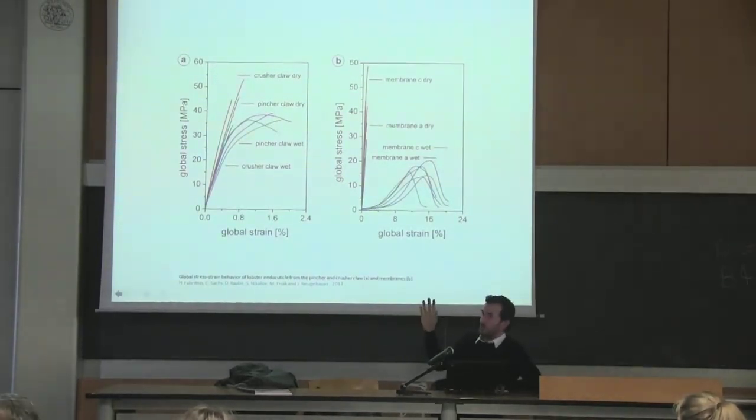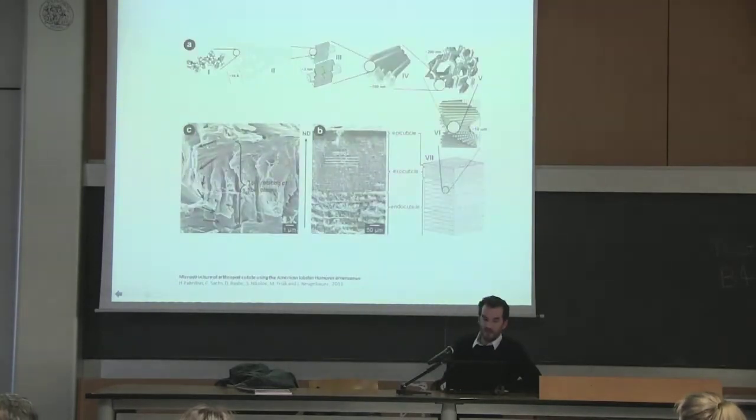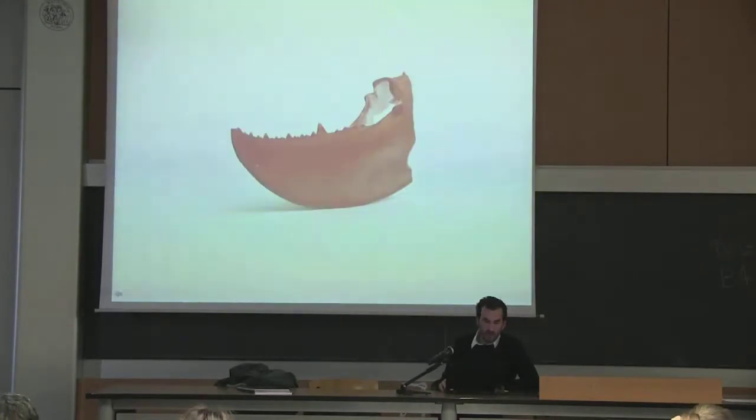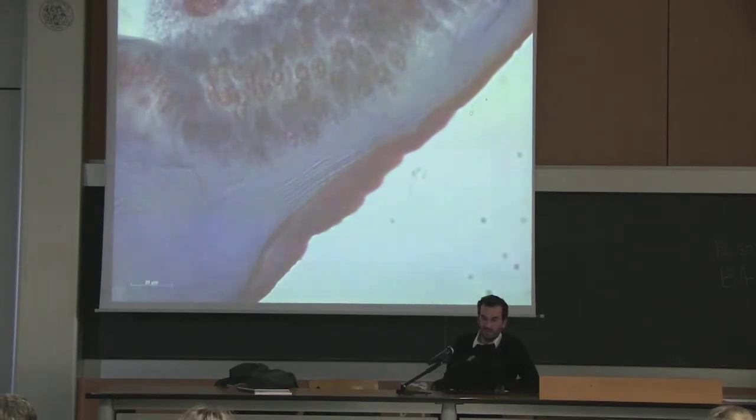But it's also interesting to note that these very different material properties are achieved by one and the same material. So the whole lobster shell, including the eyes, is made from one material only, which is chitin fibers embedded in a protein matrix, which means it's a natural composite material that allows for all this differentiation on the material level. So what we did is we investigated different parts of the lobster with the students and the biologists under the microscope again, and extracted the principles behind this performative fibrous differentiation.